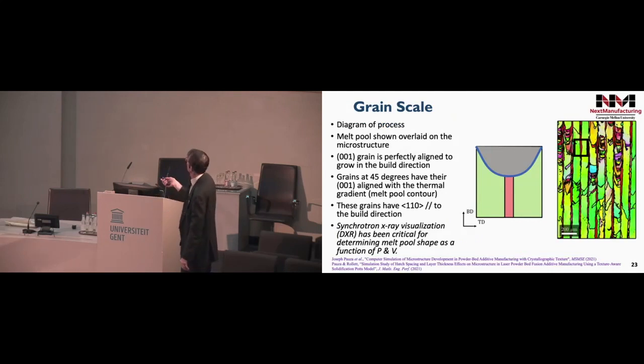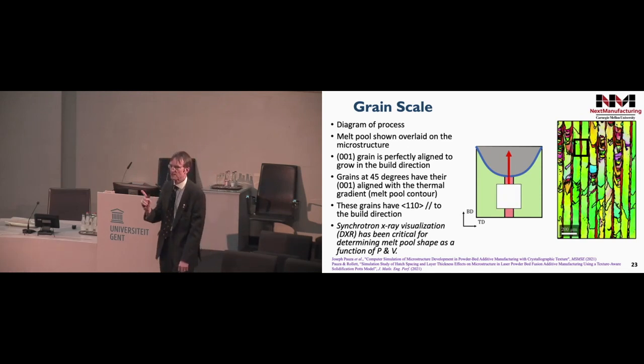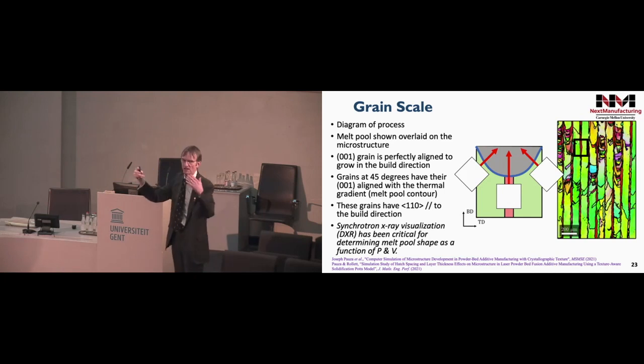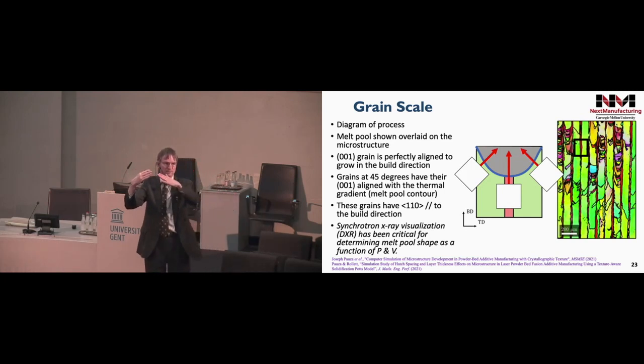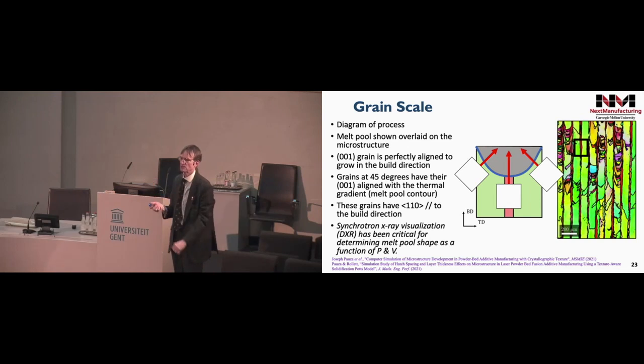So this on the right is the example of the medium speed, and then magnifying that and making a cartoon of it. And if you think about, and the build direction is up, of course, if you think about grains growing from the very bottom of the melt pool, well, they can grow with 100 going straight up, hence the long red grains. But the grains at the sides are mostly constrained to grow at an angle. And that then immediately explains why you see this green color and the 110 texture in the bulk of the grains in between. And so that's the sort of first order explanation of why we see the microstructures that we do.